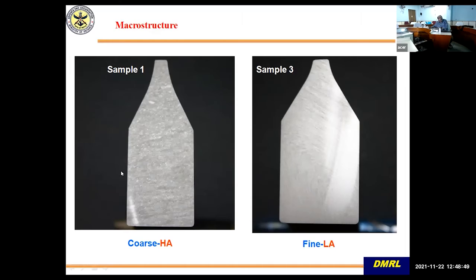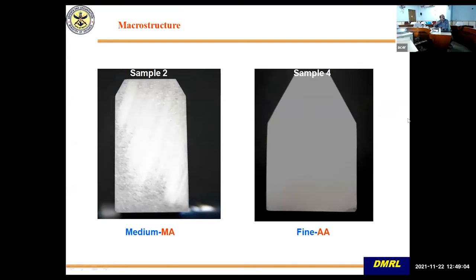And when we look at the macro, we etched it and wanted to see is there a difference macro wise? There is a slight difference, but not too much. This is again different materials from differently processed rings. And then ultrasonic attenuation was measured. Now, why we were doing this is because there is a lot of material flying around in US engines which were processed before microtexture was understood to affect fatigue and dwell fatigue properties. So they wanted to assess non-destructively whether it is possible to pick out material with higher microtexture and material with lower microtexture, because material with lower microtexture is better as far as fatigue and dwell fatigue are concerned.